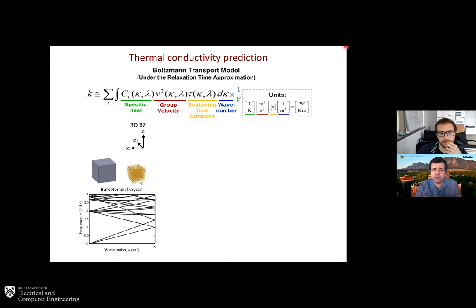What is important to observe here is, first of all, the concept of thermal conductivity is intimately dependent on the phonon band structure. That's number one. And number two, it is highly affected by this quantity here, the group velocity squared. Now, of course, we know that the slopes of the dispersion represent the group velocity.